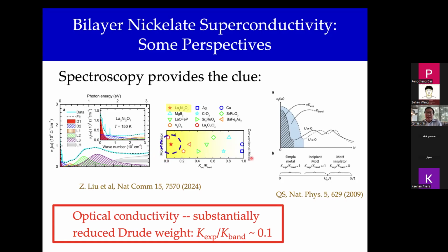For the cuprates at half filling, it would be a Mott insulator, so this ratio is 0. For very weakly interacting systems like silver, copper, what you measure for the Drude weight is roughly what is expected from the non-interacting band structure, so this ratio is 1. So very good metal, Mott insulator, and clustering around here would be a calibration for the typical bad metal behavior. And these are kind of things that were also used as a meter for calibrating the effect of interactions for the iron-based superconductors, and the nickel-based superconductors seem to belong to this bad metal regime, at least based on this calibration.